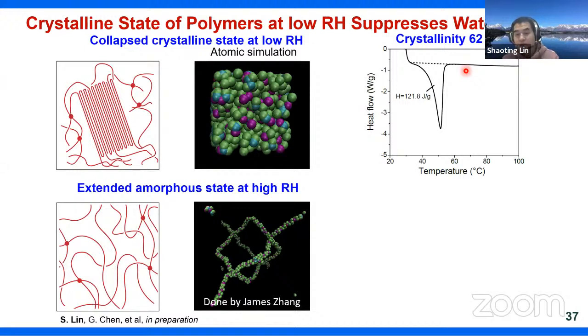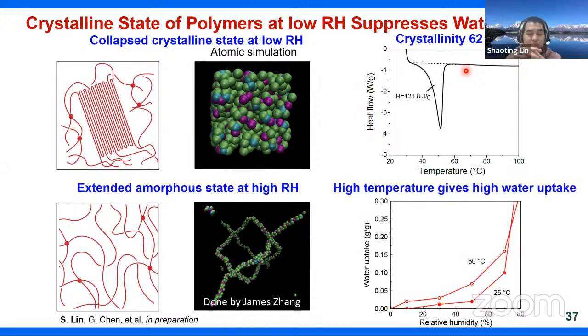Okay, so here is another interesting phenomenon. What we found is that for most materials, when heated, ideally they should have a lower sorption capacity, right? Because water at a high temperature tends to evaporate or dehydrate. But what we found for this PG material is very interesting. It has a high sorption capacity at a high temperature. So what's the reason?